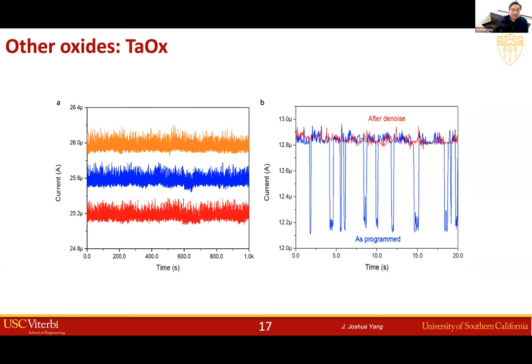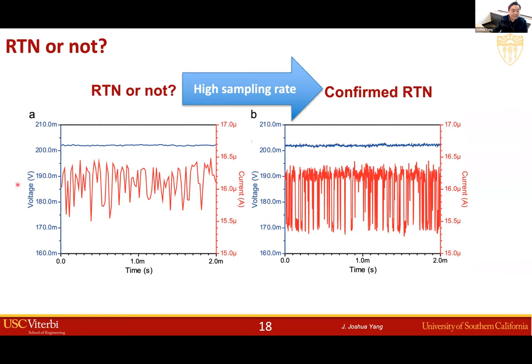Okay, so this is not just for the oxide material we use, hafnium oxide. It actually is quite general to other oxides. For tantalum oxide, you can see before denoising, large noise, after denoising, it becomes very stable. And in many cases when you see noise from your device like this, it doesn't look like RTN, but in fact, the noise is usually RTN. If you use a high sampling rate and remeasure the same noise at high speed, you can see the RTN feature start to show up. And so it is the RTN that gives us the trouble, and the denoise can remove the RTN.